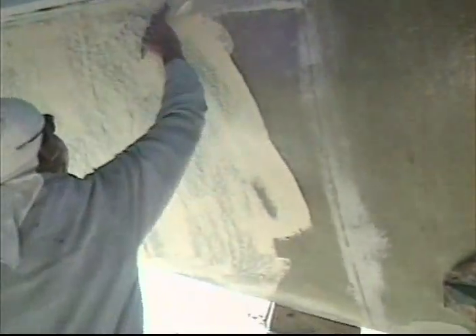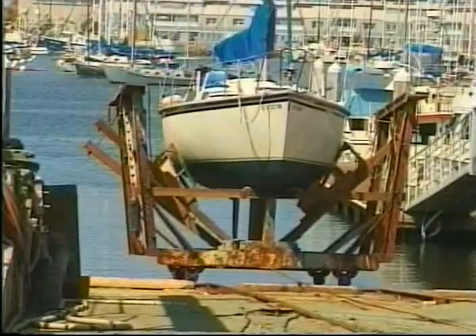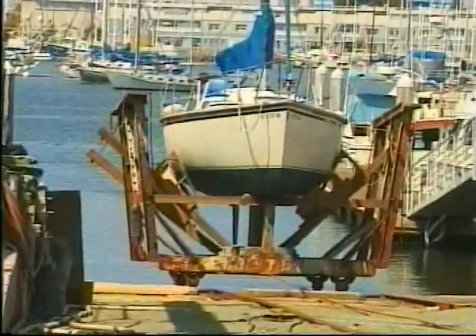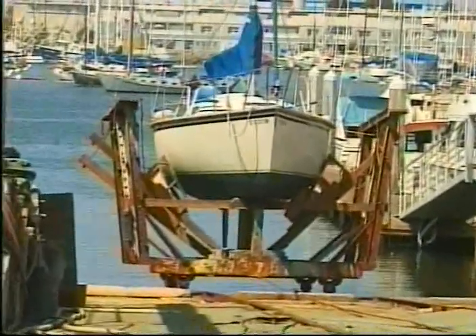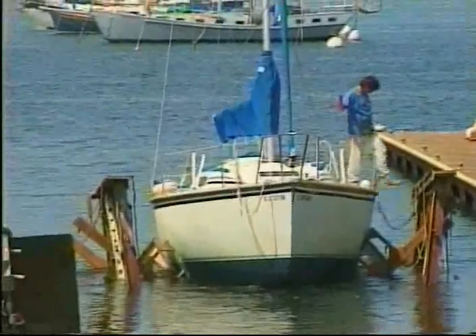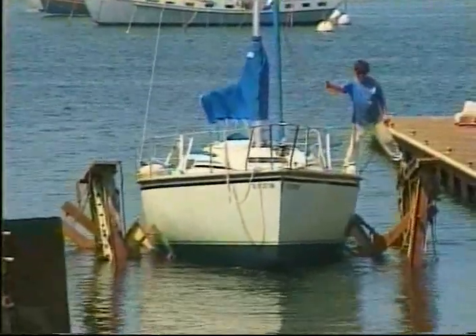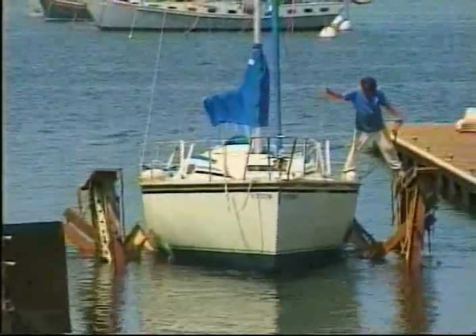After rebuilding of the fiberglass laminate is complete and the bottom is finished fair and smooth, the final coats of anti-fouling paint are applied. The vessel is returned to the water with a new bottom of modern materials. Tests indicate that the newly repaired hull will last 25 to 30 years.